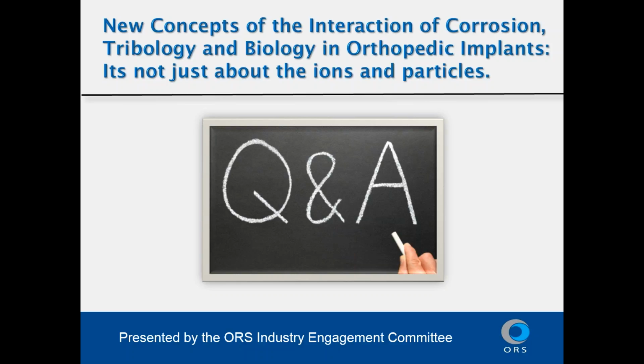Okay, next question. To what extent do you think corrosion at the head neck taper is due to cell-induced corrosion and not regular MAC? For example, 1% to 10% or more. Well, I think the premise of the question may be a little off. Mechanically assisted corrosion is a mechanism that is ongoing whenever you have abrasion of oxide films in the presence of an electrolyte of this sort. As long as there are those conditions to lead to mechanically assisted corrosion, it will occur.